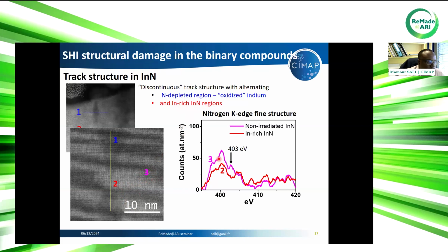If you compare the two fine structures, we can see that the peak at 403 electron volt, which is due to the pi transition in this material, disappears after irradiation in this region. So by irradiation, we destroy a little bit the structure of indium nitride in this region.